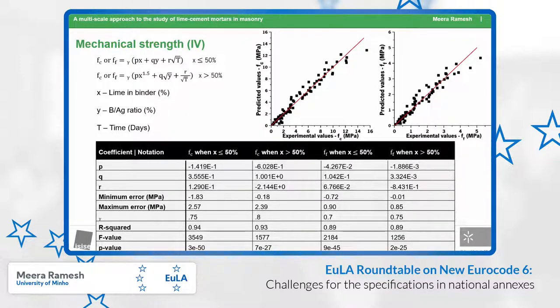However, we are aware that this is valid for only our given set of materials. So if the materials were changed, the equations would have to be recalibrated. And it would take a while before we could generalize these equations. But it definitely sets the first steps towards a generic model. We found out that these equations could explain the strength reasonably well, up to an error of plus or minus 2 megapascals. And what you see in the graphs on screen are basically predicted values versus experimental values.